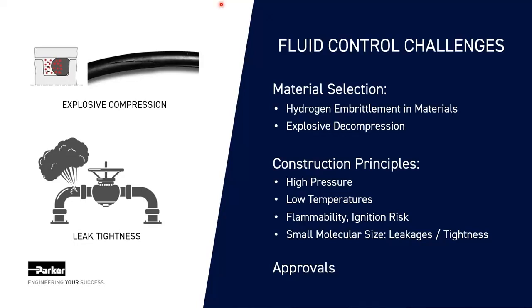Another important factor to stress is the explosive decompression. Hydrogen gas, due to its small molecular size, can permeate into the elastomer materials. Explosive decompression, also known as rapid gas decompression, is a failure mechanism that occurs in elastomer seals and O-rings when there is a rapid reduction in pressure of a gaseous medium. When a gas permeates into an elastomer seal and then rapidly expands upon pressure release, it can lead to fissures and seal failure. Absorbed hydrogen expands rapidly within the polymer, leading to internal blister fractures or macro cracks.